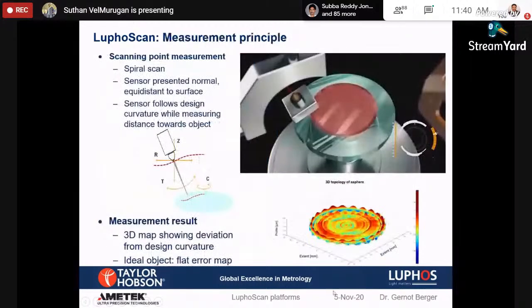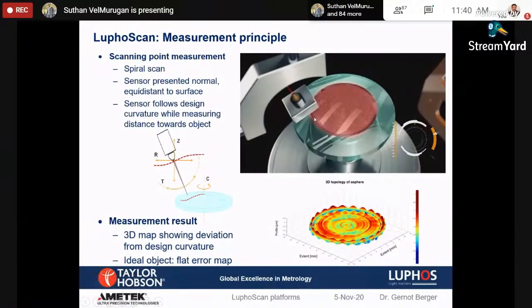So this is how the probe is going to release the laser beam, and there is a receiver which can receive the laser reflection from your sample, and the spindle is going to rotate, and the probe will move in only one axis, which means it will take a spiral scan and can collect the entire optic's 3D surface. You can see the example of how it measured. This is the heat plot or 3D plot of the measurement.